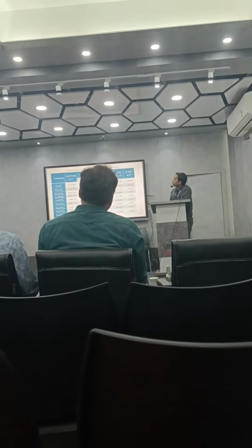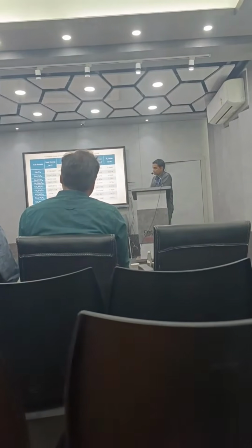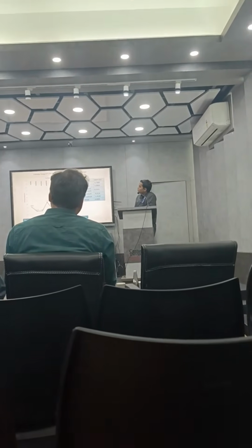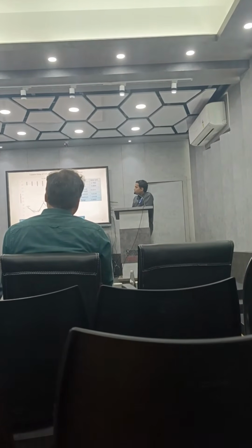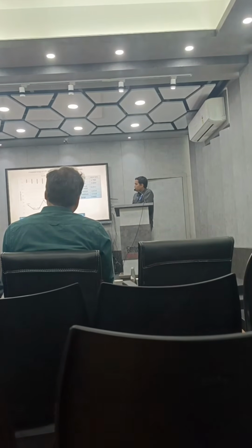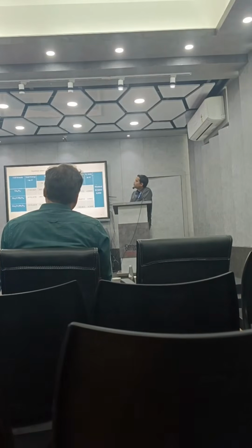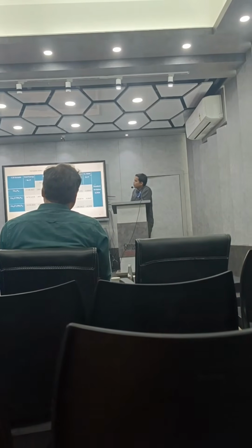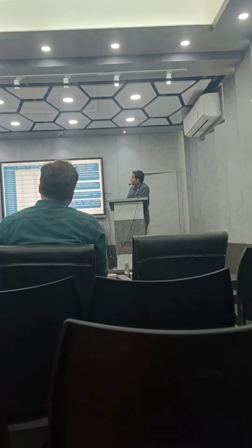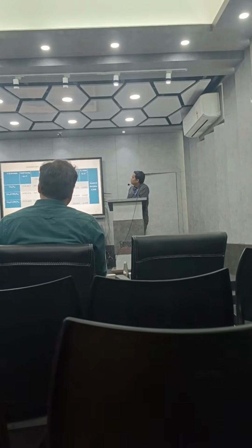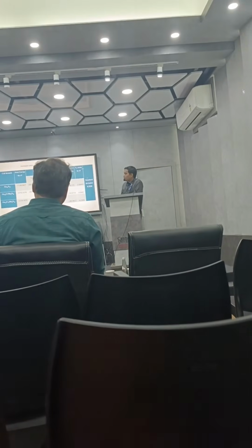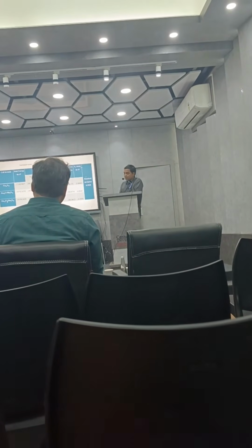This one indicates the most stable configuration. Then the formation energy of substitution at the gallium side with gallium vacancy: we found that chromium doping, and vanadium doping with gallium vacancy, exist with the lowest formation energy. Then we calculated the co-doped system, that is both chromium and manganese doping. We found that both show negative formation energy, so all these structures are stable.